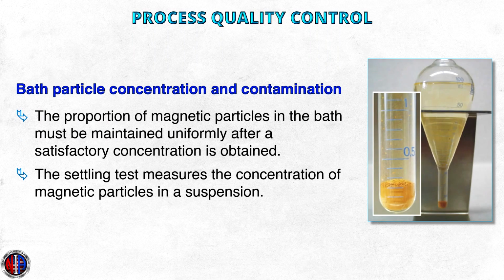Bath particle concentration and contamination. It is important that the proportion of magnetic particles in the bath be maintained uniformly after a satisfactory concentration is obtained. If the concentration varies, the strength of the indications will also vary, and interpretation of an indication may be erroneous. Fine indications may be missed entirely with a weak bath.